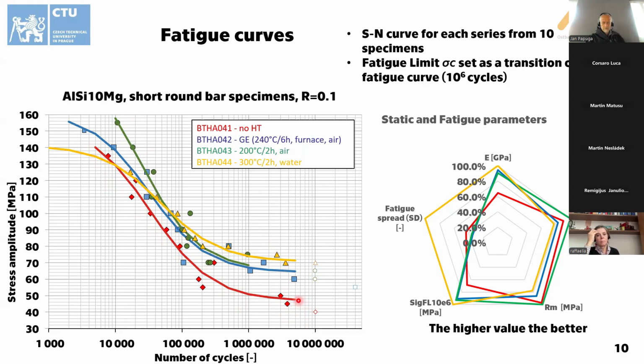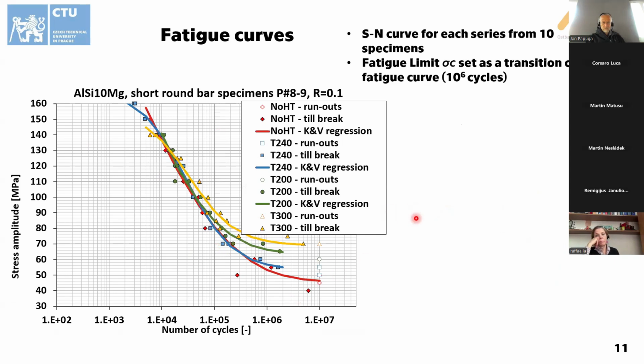But this is when you're not considering the printing position. If you use fresh powder and a more stochastic approach to the printing position, you can see that the nuances between each curve and each heat treatment are much less visible. Particularly for the T240, which is recommended by the manufacturer, and the non-heat treated variant, they are almost negligible. They are visible only in the run-out condition, and maybe around 1 million cycles. But the results for the T200 and T300 stand out to be the best option in this case, as it sits right now. But maybe when we do these tests in the future, the results will be totally different. So this is just a question for the future, Martin.